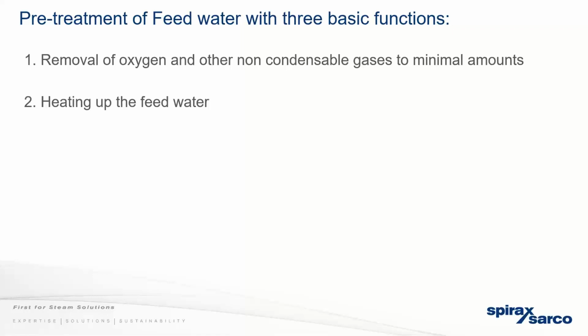Then there's heating up of the feed water. If you have hot feed water going into a boiler, you make sure that you don't kill the boil. The boiler still keeps on generating. The other benefit of heating up the water is that it gets rid of the non-condensable gases, which is air in the water itself. Then after you've removed oxygen and heated up the water, you would want to store it in that condition, so that the temperature doesn't go down and more air doesn't get into the feed water either.